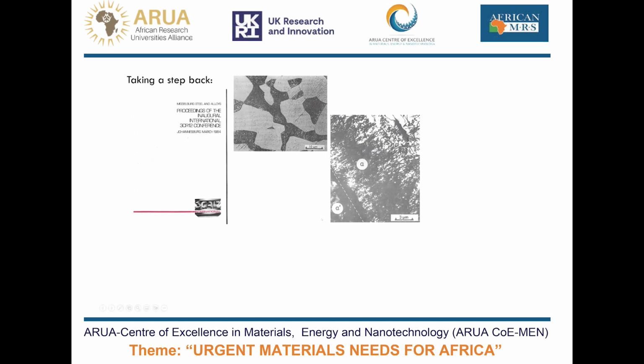the right, transmission electron microscope micrograph shows that there's a very, very high dislocation density that occurs in the ferrite immediately adjacent to the martensite. And that, of course, produced a whole lot of mobile dislocations, which gave the steel superb ductility.